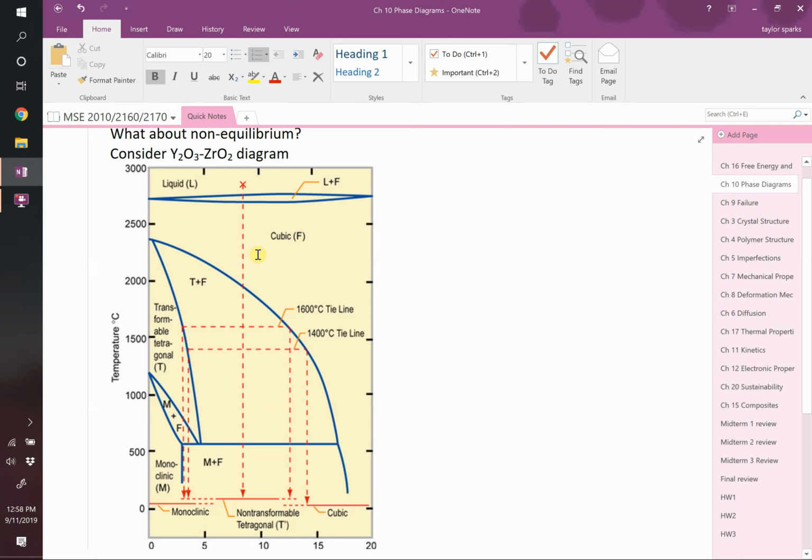So when they say that you've got a diamond ring, right, but it's not diamond, it's cubic zirconia, how on earth are they making that? Well, there's lots of things that they can do. For one thing, you could heat it up to 2,500 Celsius, let it equilibrate so it's in the cubic structure, and you could try and quench it.